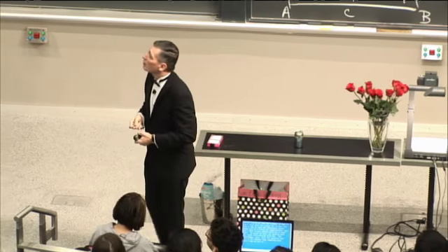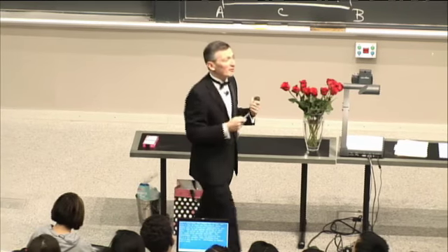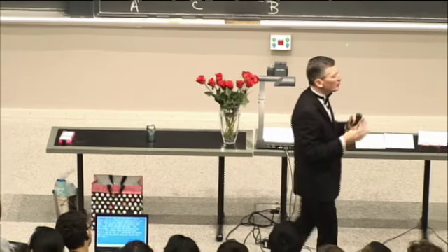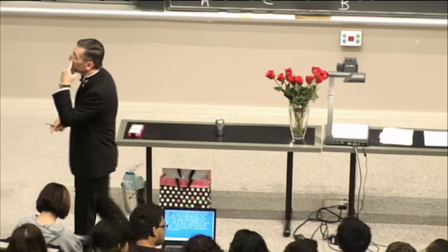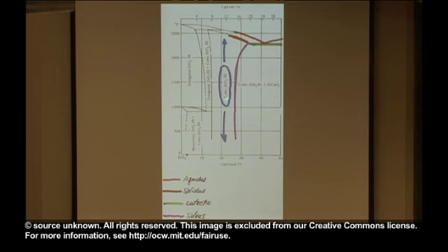Christmas is coming, and I told you that phase diagrams would save the day. We saw that the cubic zirconia was stable in pure zirconia only at temperatures above 2,000 centigrade, which is useless for a ring or other such pieces of jewelry. But by the addition of calcium oxide, we stabilize the cubic form of zirconia all the way down to room temperature. And now we've got the high index of refraction, clear, colorless gemstone that passes for diamond. Poor man's diamond, cubic zirconia.